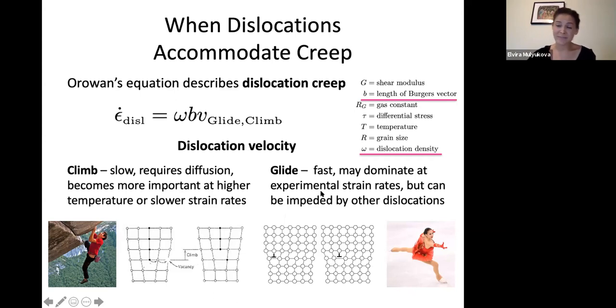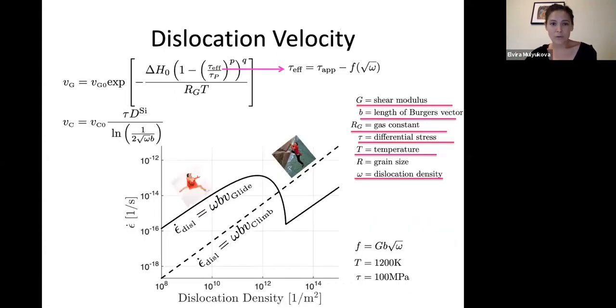So this process is faster at high strain rates. For example, at typical experimental strain rates, this may indeed be the dominant deformation mechanism, or dominant dislocation motion mechanism. However, glide is sensitive to the presence of other dislocations. So as it's trying to move through its plane, encountering other dislocations may slow it down significantly. So this process may become slower the higher the density of dislocations. So that was a qualitative description.